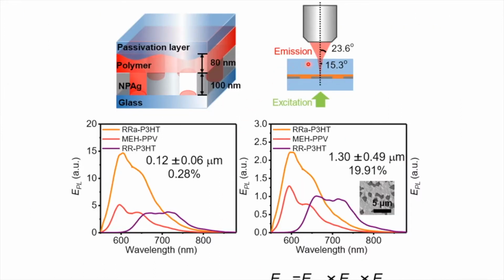We studied the impact of these metasurfaces on the polymer fluorescence, first using a fairly low numerical aperture microscope objective. So we're only collecting a fairly narrow emission cone, mostly the out-of-plane emission from this sample, where the polymer coated the metasurface and it was encapsulated on either side. You can see that the regiorandom P3HT spectrum is strongly enhanced. So this is the enhancement in the photoluminescence spectrum of the metasurface compared to planar silver. However, for the MEHPPV and the regioregular P3HT, it's not as enhanced, even though it is enhanced reasonably well compared to planar silver. This was for the small pore sample.